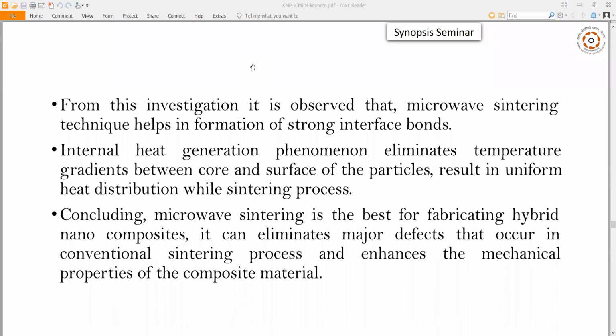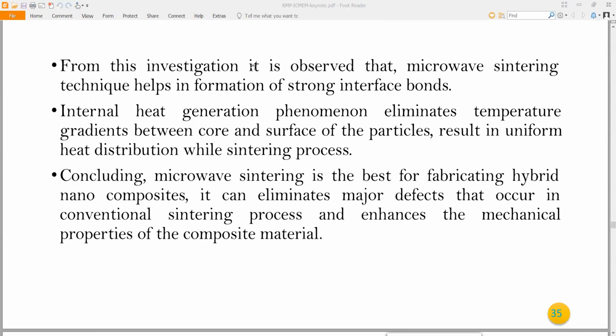And our conclusion is this: from this investigation, it is observed that microwave sintering technique helps in formation of strong interface bonds. Then internal heat generation phenomenon eliminates temperature gradients between core and surface of the particles, resulting in uniform heat distribution while sintering process. Then concluding, microwave sintering is the best for fabricating hybrid nanocomposites. It can eliminate major defects that occur in conventional sintering process and enhances the mechanical properties of the composite material.